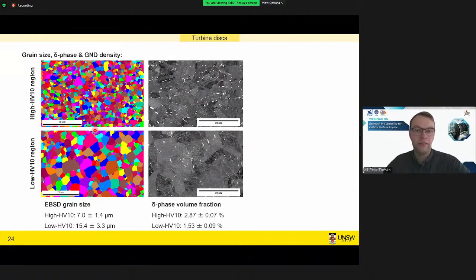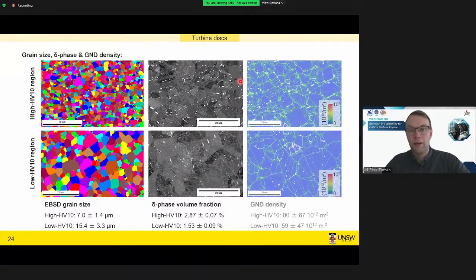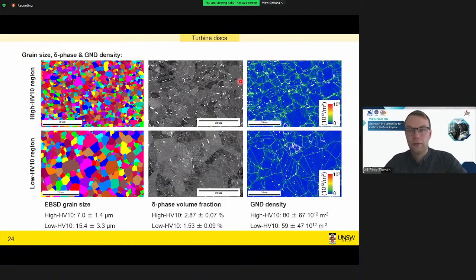If you look at the delta phase fraction, it's already low because these are directly aged turbine disks. But in the low hardness regions, we find even lower delta phase fractions. If you look at these bright platelets again. And in addition to this, we can also plot our geometrically necessary dislocations again, and we find that these larger grains contain much less dislocations.